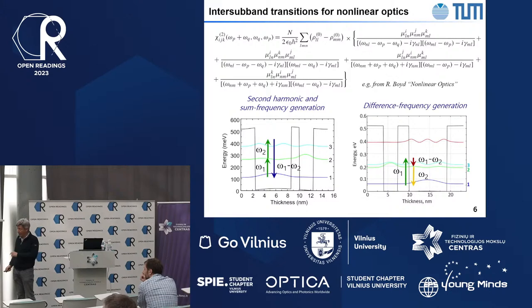That's one effect. The second effect is that the effective mass of electrons in semiconductors is significantly smaller than the free electron mass. So in this material system, indium gallium arsenide, aluminum indium arsenide, that we used, the effective mass of the electron in the well is 0.04. And you know that oscillator strength has 1 over effective mass in the denominator, which means that for a given transition energy, our dipole moments are going to be square root of 1 over effective mass stronger. So 1 over square root of 0.04 is about 5 times stronger for a given energy. And we have 3 of those. So that's another reason why you boost. And finally, of course, you move close to resonance, although being too close to resonance is also bad. That's a third effect that leads to this giant response. I see. Thank you.